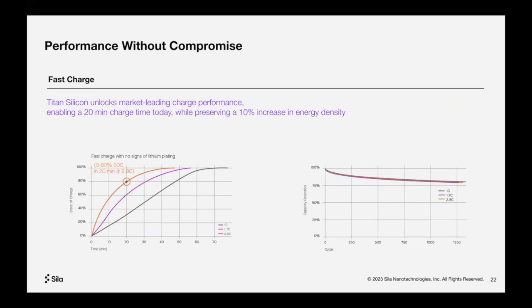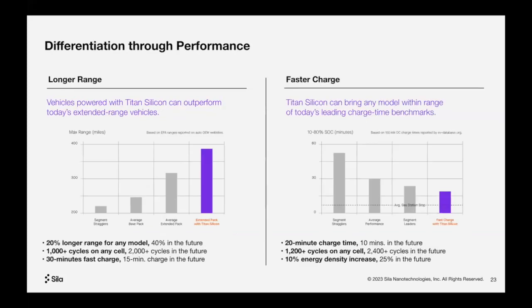And then just to show you a slide on fast charge, you can see different charge rates starting with 1C, the green line, and then going to 2.8C with that orange line. That 2.8C is equivalent to 20 minutes. That's how we're doing the fast charging. And then on the right, you can see what kind of cycle life we get from it. Again, we're getting over 1,000 cycles with no impact based on the different charge rates. So the material is quite impressive for handling higher energy density and the faster charge.